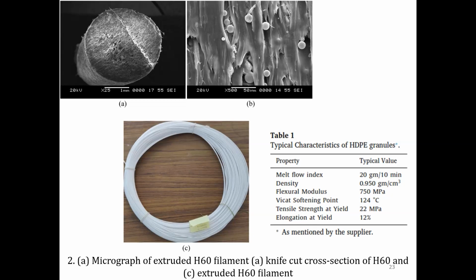So, as I mentioned earlier, you can eliminate these voids completely if you use vented type extruders. But if you have a non-vented type, these additional porosities get transferred to the printed samples, which we did observe for a three-phase syntactic foam. Three-phase means one phase is matrix, the second phase is hollow microballoons, and the third phase is void, the air entrapment present there. These might enhance damping capabilities in three-phase syntactic foams.